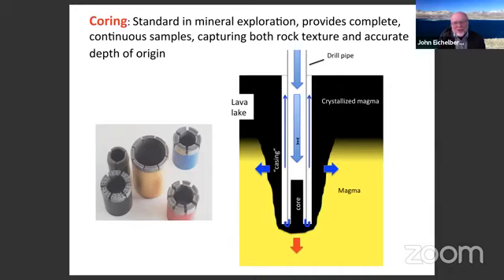It's cool. And when you get into molten rock, you're actually making a glass casing around the borehole. Notice that you've got to select the right penetration rate. If you're very slow, you're not going to get good quenching. It's going to be slow cooling. And God forbid, if you go too fast, you're going to outrun this quenching front and end up in the soup, and you will be stuck.